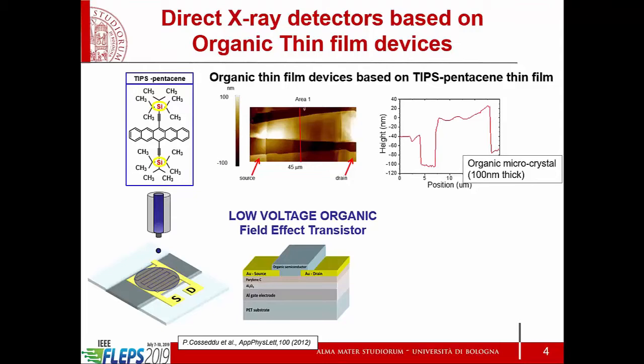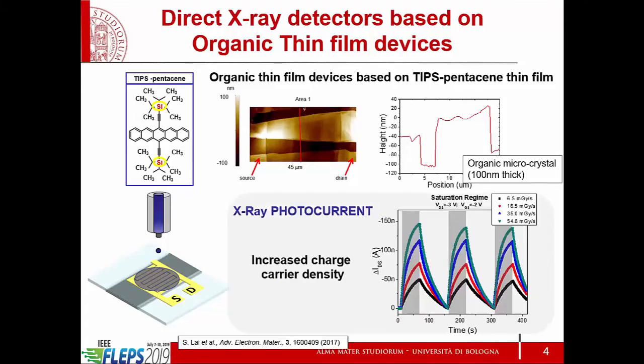How can you improve this very simple two-terminal device? Well, we use the transistor as a bottom structure with a very thin gate dielectric so that, of course, it stays flexible, but also the operating voltage remains relatively low. That is interesting because, as you can see, if we operate it with the on-off switching X-ray beam, we see indeed the photocurrent going up and down. The different curves refer to different dose rates, so it's the intensity of the X-ray beam arriving on the sample.